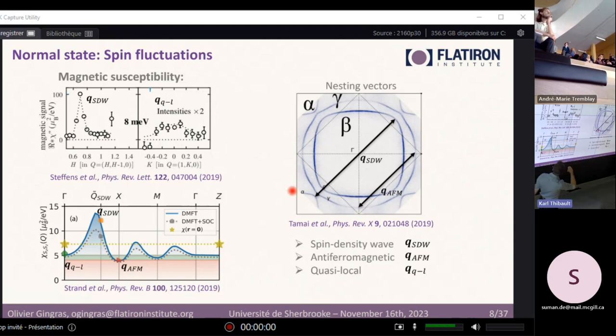And the final thing I want to mention is the presence of strong spin fluctuations in this material. So if you do inelastic neutron scattering and look at the magnetic susceptibility, which shows you the momentum dependence of the spin fluctuations, you will find large peaks that show that there are strong spin fluctuations. And if you want to calculate this using simply DFT, DFT will give you certain nesting vectors, which will give rise to these peaks, but they are not exactly reproducing the experimental evidence. Instead, you need to incorporate vertex corrections through the DMFT to have a great agreement with experiment.